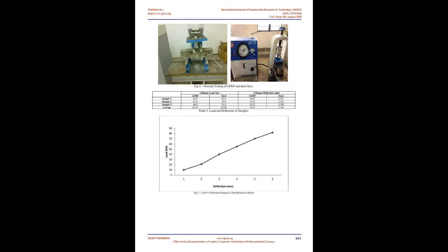1. Tensile strength. GFRP bars are anisotropic due to the orientation of the fibers, which are fixed along the longitudinal axis. They have high tensile strength, 500 to 1200 MPa, compared to steel rods, 250 to 550 MPa. Their strength is controlled by their diameter and is inversely related to it. This is due to the phenomenon of shear lag. The shear lag in the bar can explain the variation of stresses from the center to its surface. According to experimental determination, Gangarao, 1991, the stresses at the surface are maximum and minimum at the middle, due to the same phenomenon. GFRP bars are relatively insensitive to normal temperature fluctuations. However, at temperatures above 200 the strength decreases.